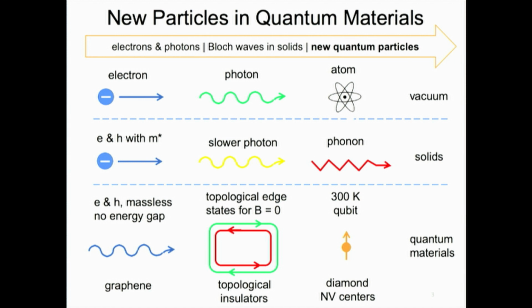And the third type that we work with is called color centers in diamond. Originally nitrogen vacancy centers, but other centers like silicon and germanium and even lead are interesting. And they produce colors, like a ruby is actually a chromium color center in aluminum oxide, Al2O3. It's a nice red color, but it works like individual chromium atoms are giving you that color, just one by one. They're far apart. And it turns out that in diamond, these color centers act like excellent quantum bits of information, the spin on them, even at room temperature.